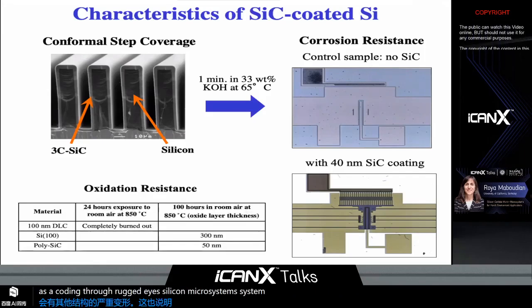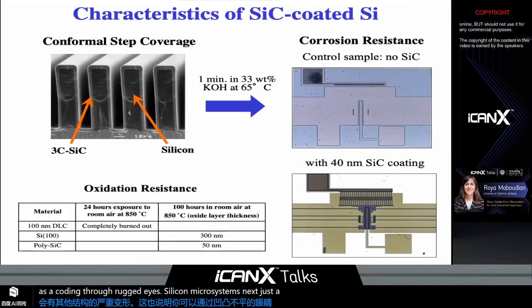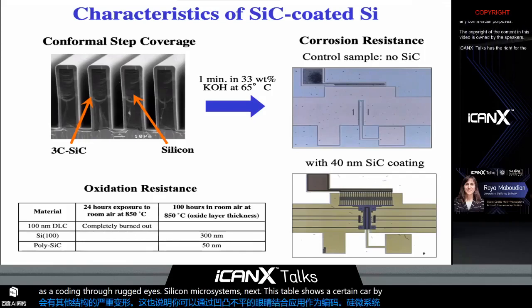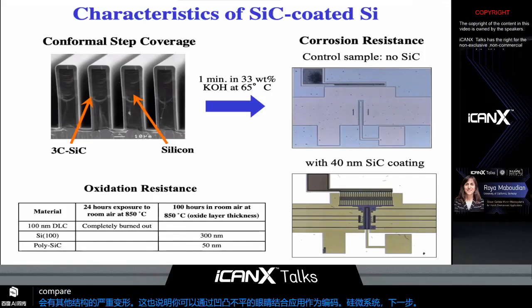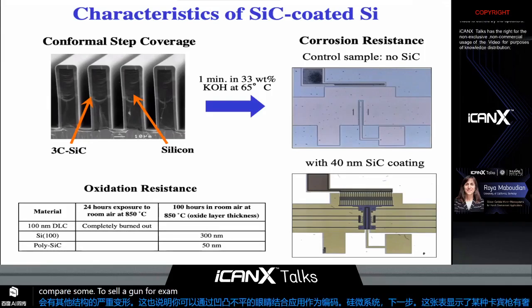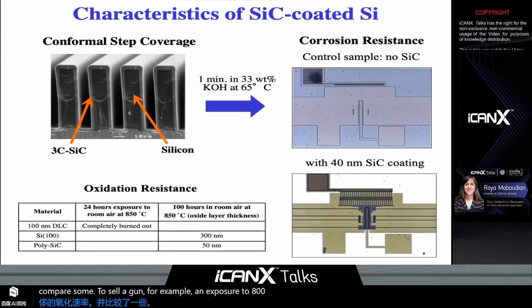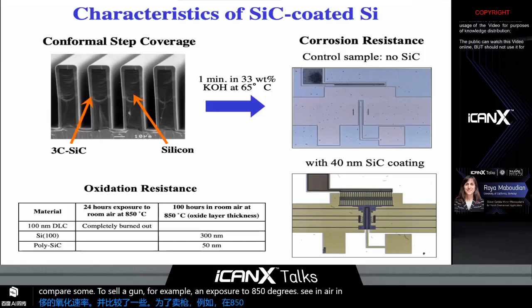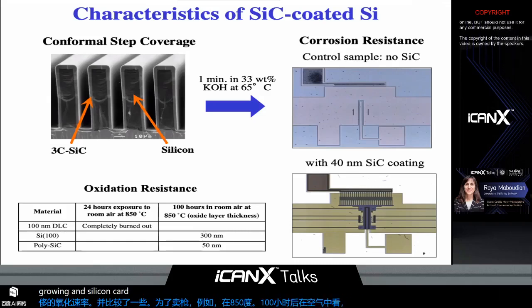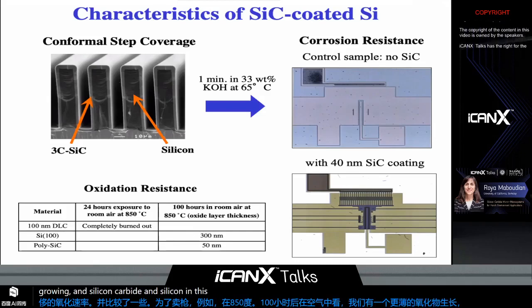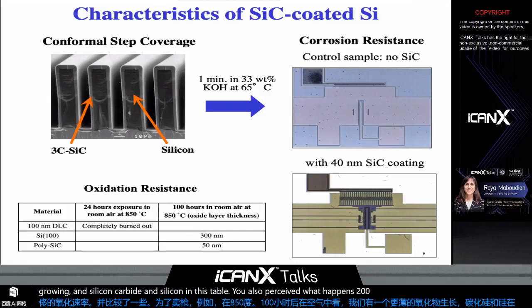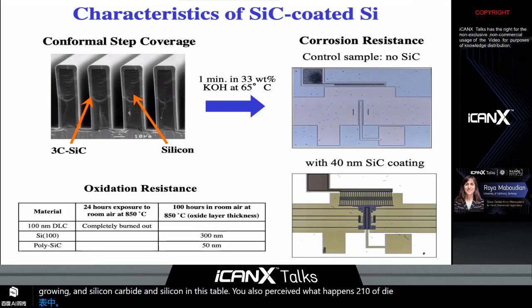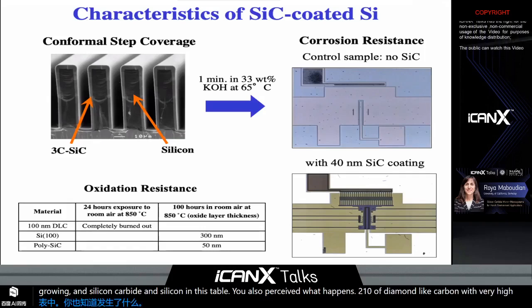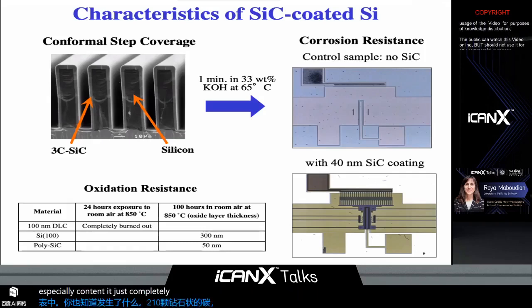Next, this table shows that silicon carbide has much reduced oxidation rate in comparison to silicon. For example, upon exposure to 850 degrees C in air, after 100 hours, we have a much thinner oxide growing on silicon carbide than on silicon. In this table, you also see what happens to 100 nanometer of diamond-like carbon with very high sp3 content, which is completely burned after only 24 hours.